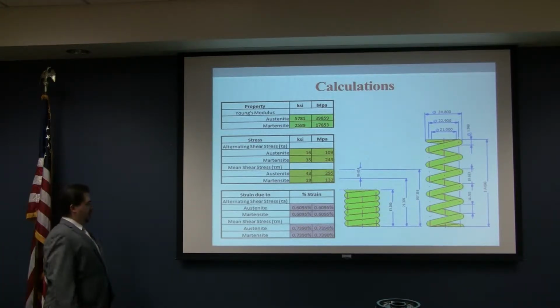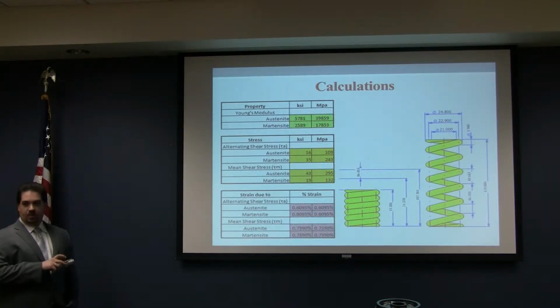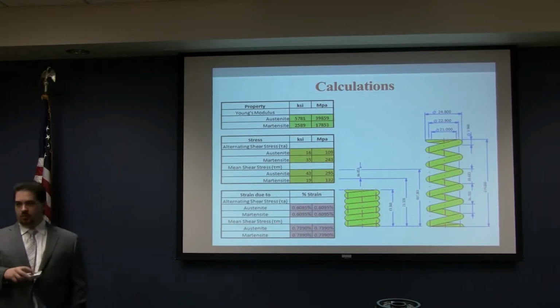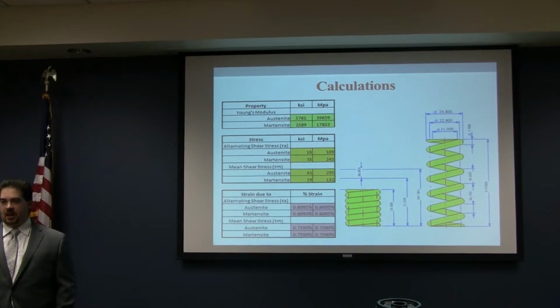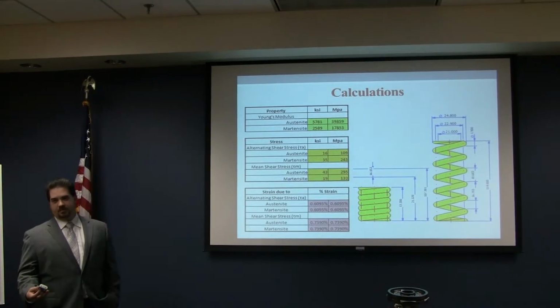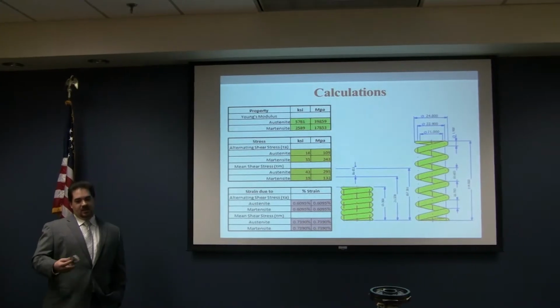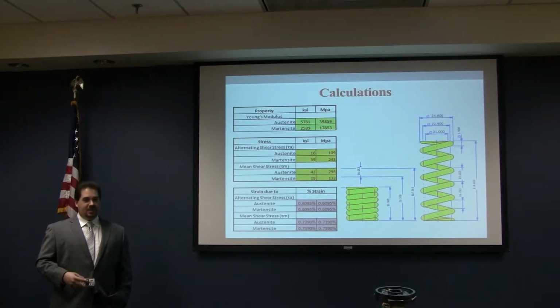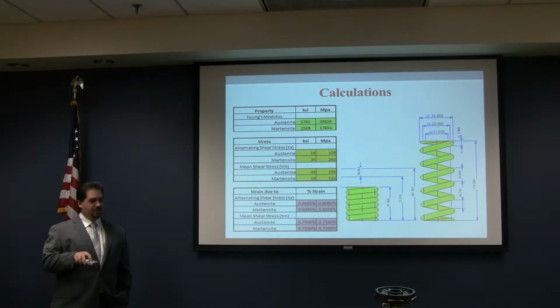These are some cursory calculations. We were operating on the premise that as long as our strain was within the 0.6 to 0.8%, we could assume that it had an infinite life. And so that's how we stayed away from the necessary fatigue calculations, which were very hairy and very nasty, considering that this is a dynamic material and we were actually carrying it through the phase change.